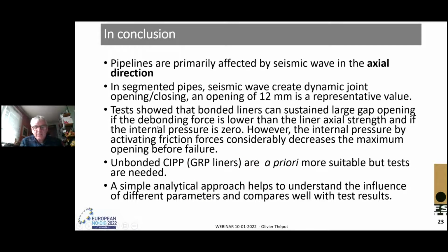Here are the main points that we can remember. Pipelines are primarily affected by seismic wave in the axial direction, first. Secondly, in segmented pipes, seismic wave create mainly dynamic joint opening closing, and an opening of 12 millimeters is a representative value. Tests show that bonded liner can sustain large gap opening if the debonding force is lower than the liner axial strength, of course, and if the internal pressure is zero.